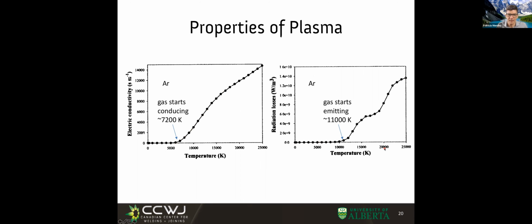Here we have a different graph that has the same horizontal axis with the same huge temperatures, but the vertical axis is the radiation losses. Those of you who took the heat transfer class might remember radiation coming from surfaces. I made the point then that we were talking only about radiation from surfaces, but radiation can come from volumes too. In the arc, each volume of the hot arc is emitting light. And what do we see? That the gas is pretty dark or transparent, not emitting light until about 10,000 Kelvin. And at 10,000 Kelvin, it starts to emit light.